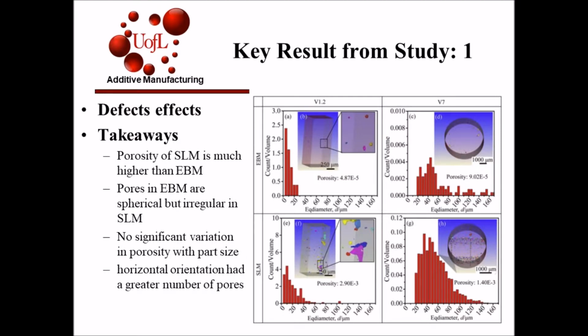Key results for defect effects. The illustration on the right shows the combined results from the CT scan and pore distribution for samples in vertical orientation of different part size. As shown in the CT scans, pores were the main defects in the printed parts. Also shown in the CT scans in the top right corner, pores in EBM samples were almost spherical, whereas in SLM they tend to be irregular in shape.